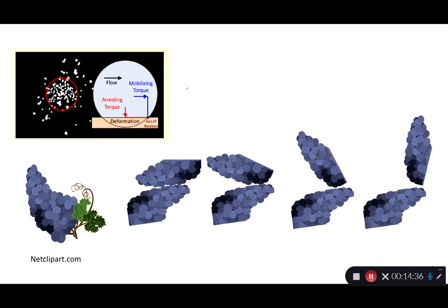And so what needs to happen, in fact, is that the analysis needs to involve a torque balance because it's rolling that initiates detachment, as well established in the literature, and including classic literature. And so the torque balance is schematicized here. The torque balance originates, of course, from fluid drag, fluid shear, but it's operating with a lever arm that corresponds to deformation of the colloid on the surface as dictated by the rheological properties of the colloid.